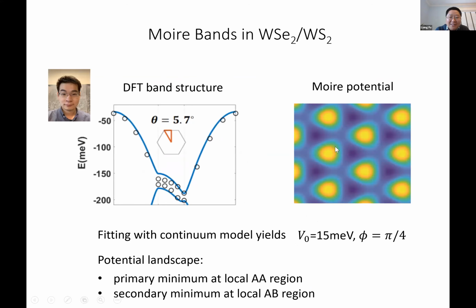And that is what happens at this twist angle, about 6 degrees. You see the bands are almost like the free particle bands, but now folded into the mini Brillouin zone, with a small anti-crossing at the Brillouin zone edges. This is a nearly free electron limit.